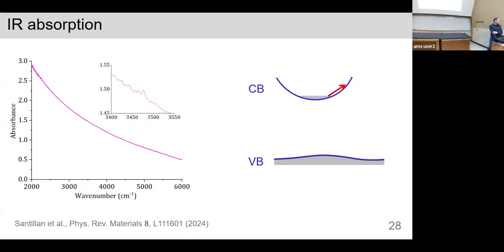This can also be seen with IR absorption. As I mentioned, free carrier absorption allows you to see the electron concentration without having to attach wires. And this is the free carrier absorption shown at low wave number, long wavelengths, it's stronger. And if you look very closely, there is a peak that appears after exposure to light. What we're actually plotting here is the difference, so the difference in absorption before and after exposure to light, to the UV light. Let's see. So that is identified as an oxygen-hydrogen impurity. So it seems that hydrogen is involved in this extremely long-lived persistent photoconductivity. So that was a clue as to the mechanism.